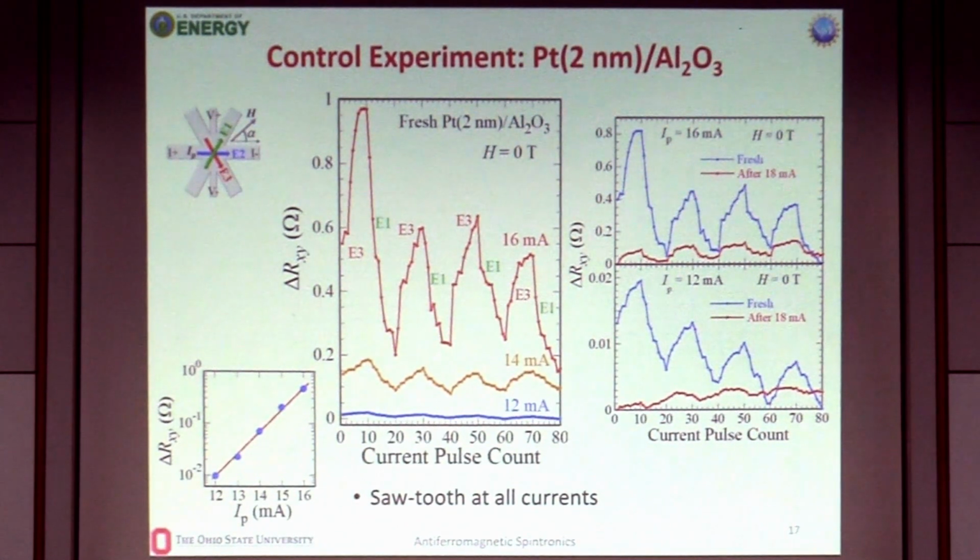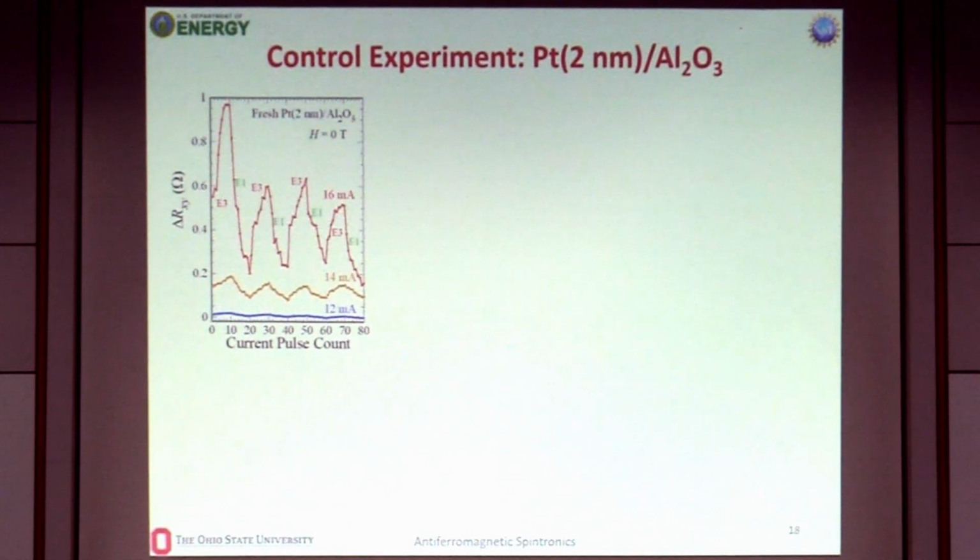If we go to higher current, we probably can reduce it further. But as we heard from the earlier talk, this could be some annealing or heating effect, where we are driving the grain boundaries or making them grow, and then a higher current reduces the number of grain boundaries. So that's another current dependence.